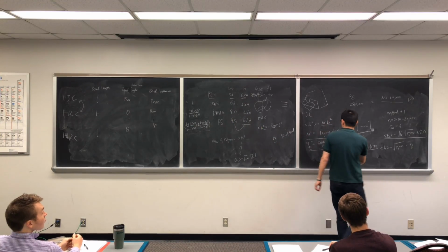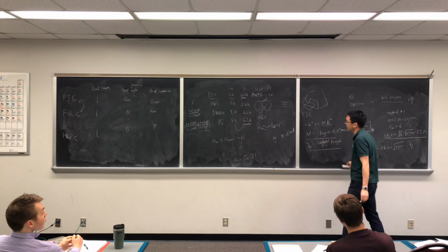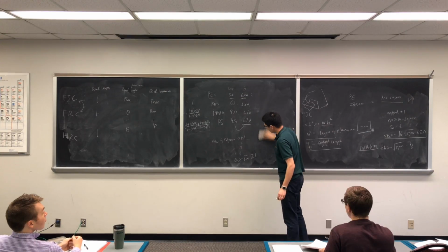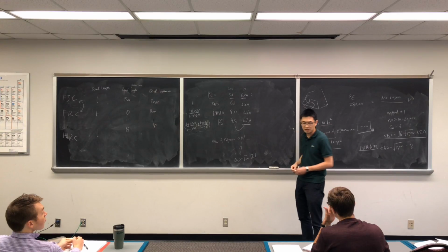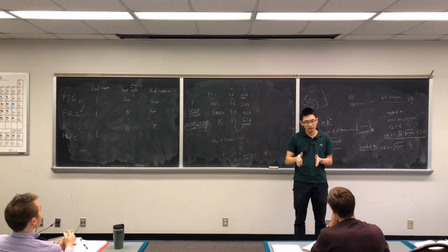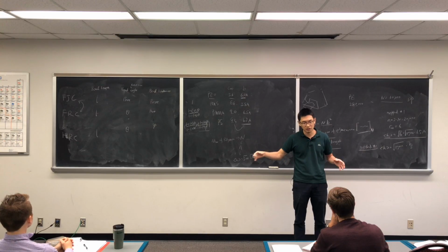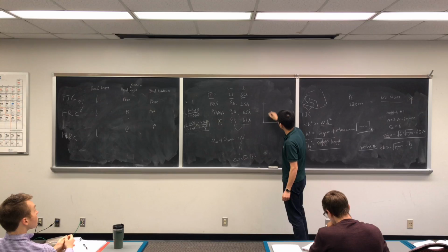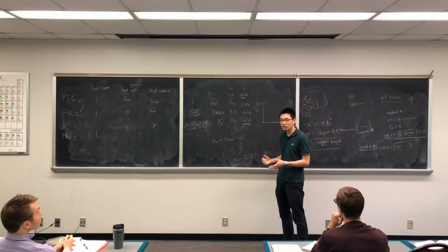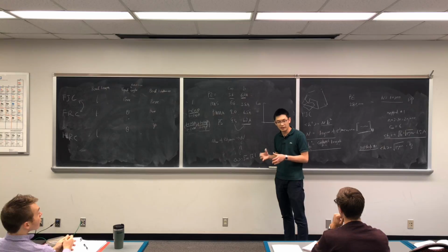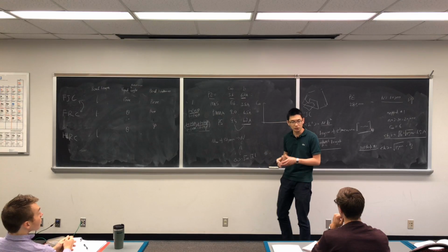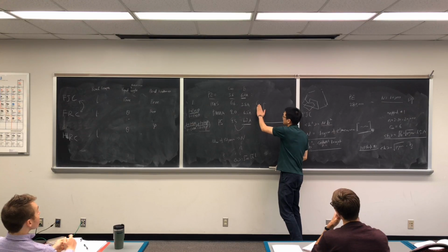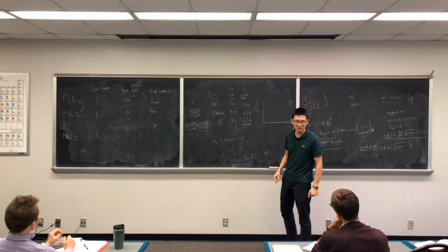Actually, in the textbook, we also discuss how C infinity depends on how long the bonds are. So let's say characteristic ratio will depend on n, or the degree of polymerization. So C infinity is not an inherent property. It needs to be used at infinity. If we remove the infinity, it's called C, or just characteristic ratio.